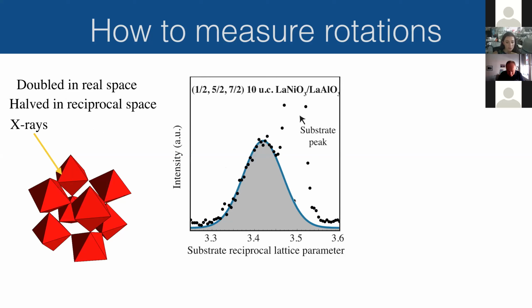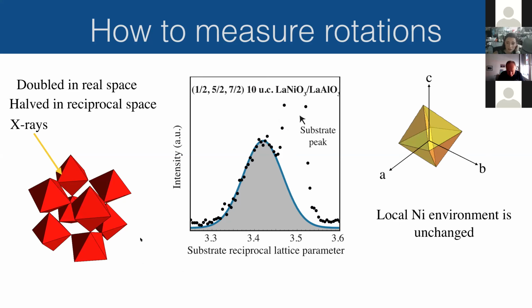So this is an example from one of my films. Here you have a 1/2, 5/2, 7/2 peak, which in a perfect cubic perovskite would not be allowed, but because these things are distorted like so, you get an intensity. You also get one from the substrate in this case because it has the same rotations. Then when you extract the integrated intensity of the signal and compare it to a simulation, what you can get back again is the magnitudes of the octahedral rotation. So that is what they did in their study, and that is what they showed.